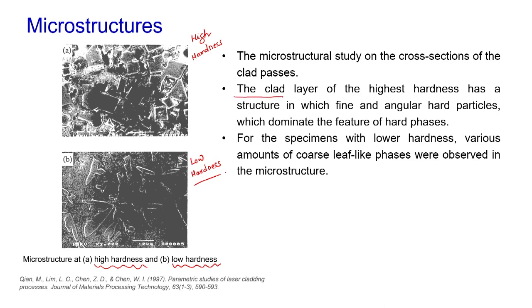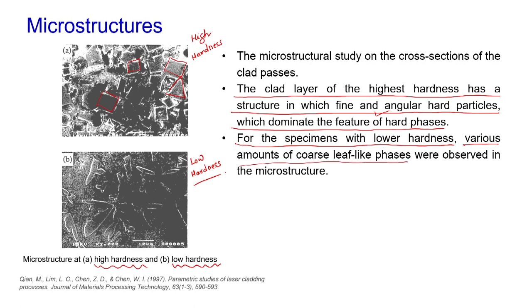What we noticed here is that the clad layer of the highest hardness has a structure in which fine and angular hard particles dominate the feature of hard phases. If you look at this microstructure, you will find that there are angular hard particles. These are all the angular hard particles that you can notice. They are fine, but they are angular, and these are the hard particles which are increasing the hardness. For the specimens with lower hardness, various amounts of coarse leaf-like phases were observed. These leaf-like phases were noticed during the optical micrograph study for the lower hardness cladded material.